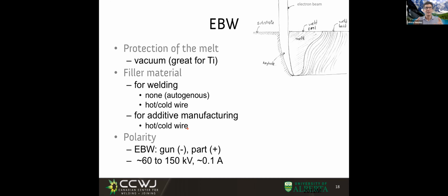Instead of being 10 to 40 volts, now we have 150 kilovolts. Let me tell you, that's very, very high. That's 150,000 volts compared to 25 volts. Conversely, the current is very low. While in welding we have 100 amps to 1,000 amps, now we're talking about 0.1 amp. But if you multiply one by the other, you end up having lots of power. Much like in laser, you have a lot of power, but you move fast, even faster in electron beams, and the resulting heat input is low.